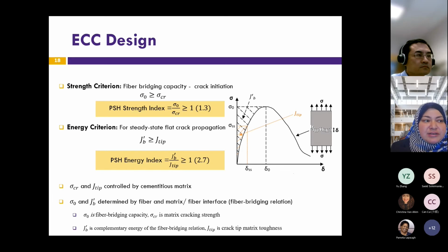Okay, so how do we design ECC? ECC design is based on two main criteria, what we call the strength criteria and the energy criteria. The strength criteria warrants adequate fiber bridging capacity upon crack initiation, while the energy criteria guarantees the occurrence of steady-state flat crack propagation. The strength criteria requires, as you can see from the equations right here, that the maximum fiber bridging capacity, what we call sigma naught, is larger than or equal to the matrix cracking strength, sigma critical.